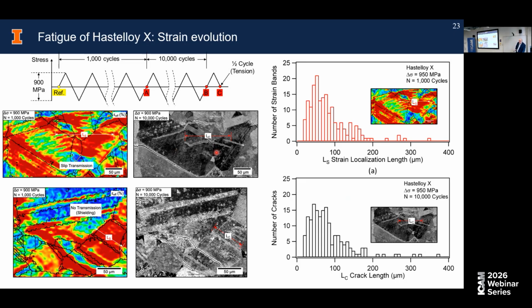So this is a 10,000 cycle image. This is a 1,000 cycle strain field. And what you see here is what we think of as transmitting boundaries. You can see here, for example, there is slip transmission across this grain, or blocking boundaries. Here, there's a grain boundary that blocks transmission.